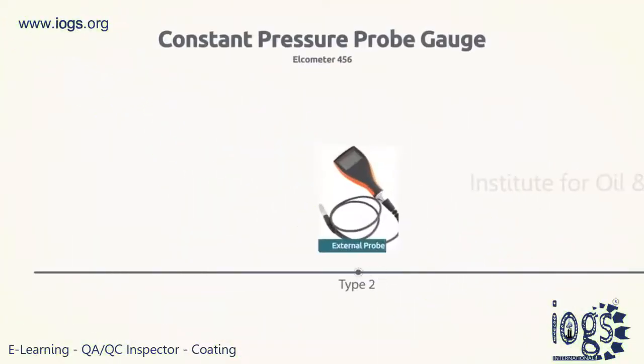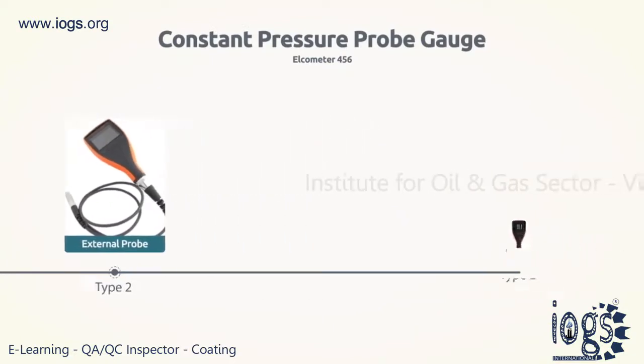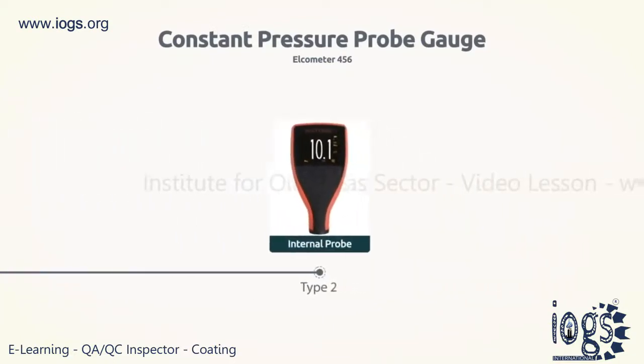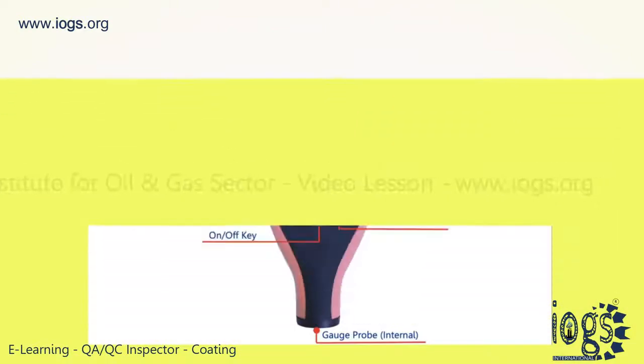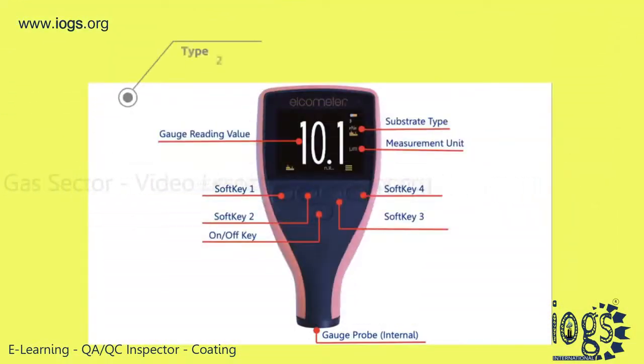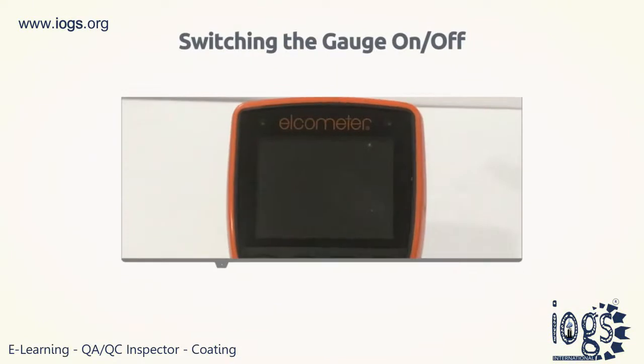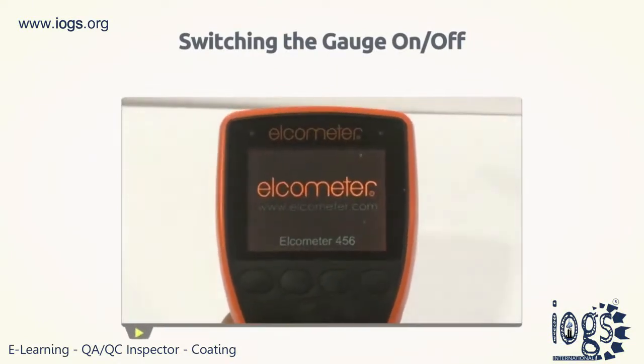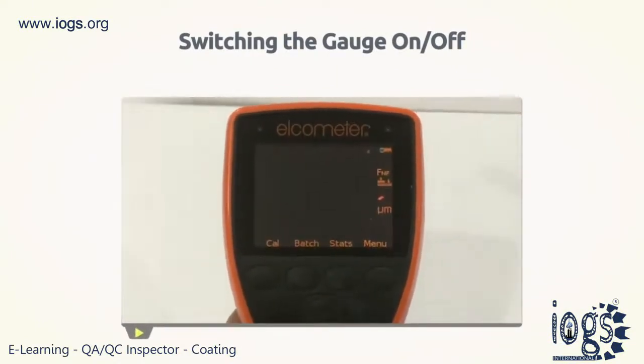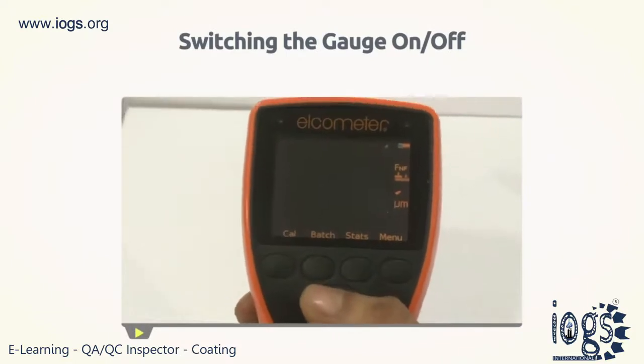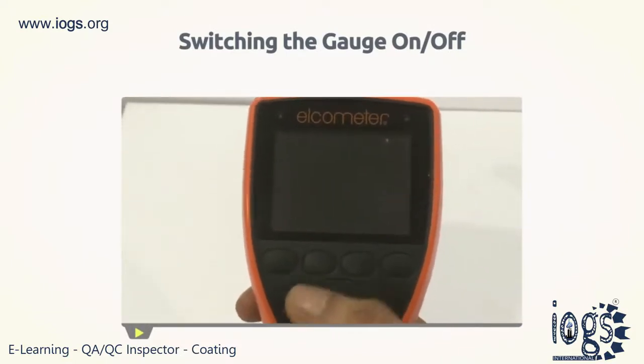The first, that is, the SSPC PA2, remains the most widely used, perhaps due to the revealing nature of the video. The video offers simple directions on how to use a constant pressure probe Type 2 gauge to determine the dried film thickness. Elcometer 456 gauge comes with a digital colored screen with soft keys designed to perform multiple functions. Pressing the on-off key for a split second will switch on the gauge, while you will have to press and hold the same key until the screen goes blank to switch off the gauge.